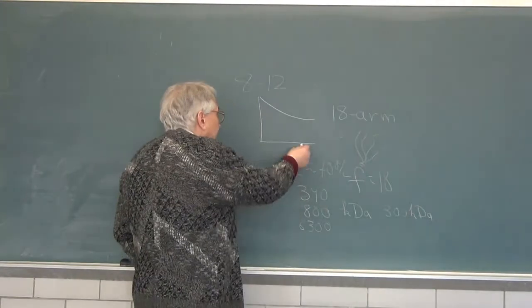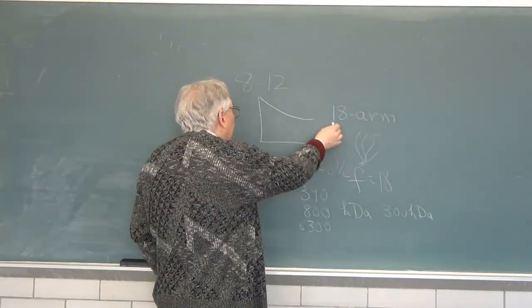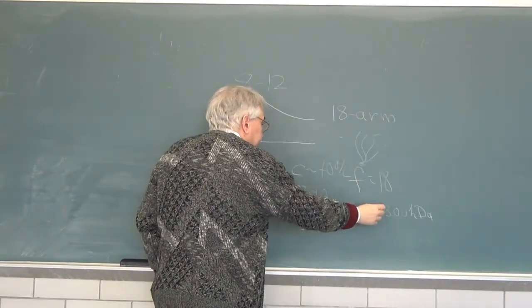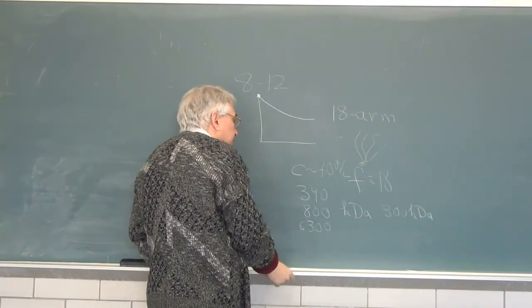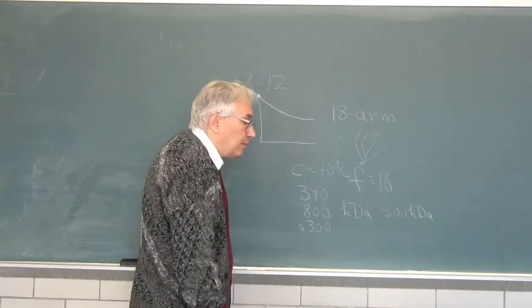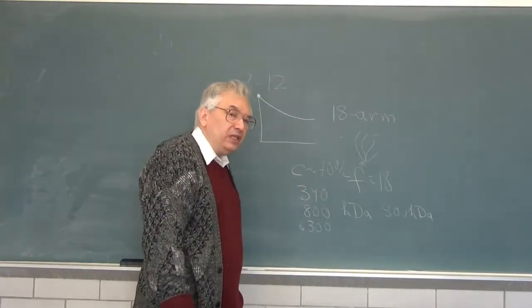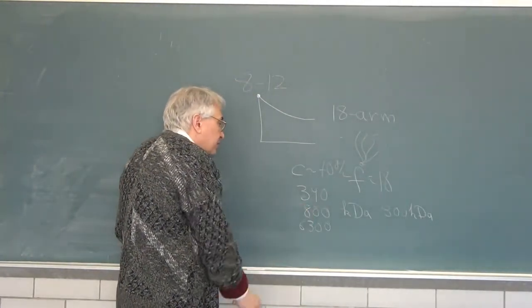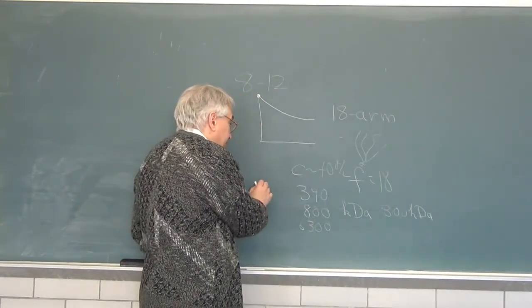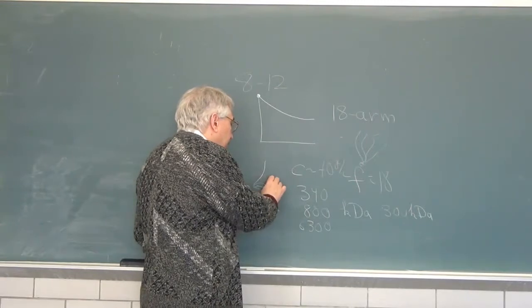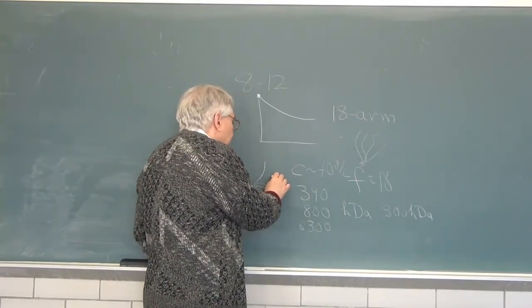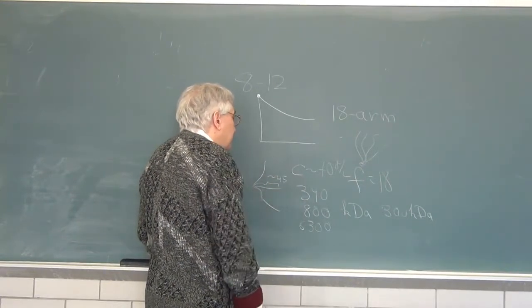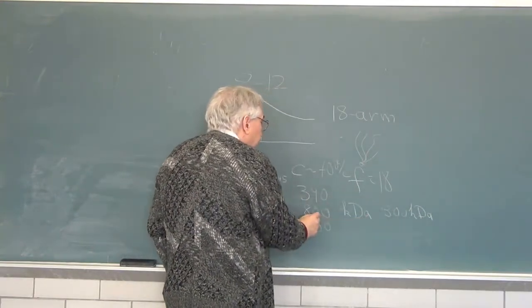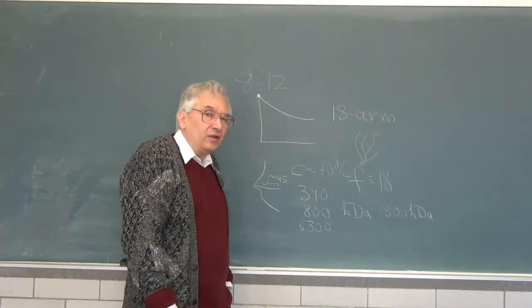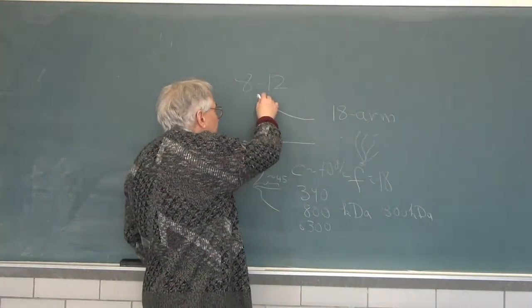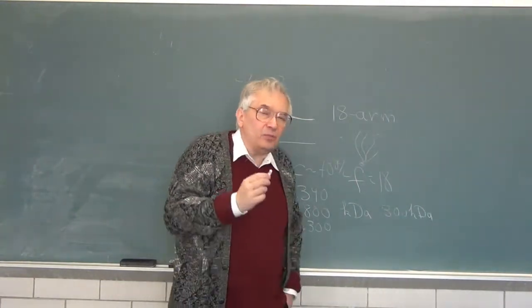They also, however, manage to find, it's the center of the three lines in the graph, a linear chain whose diffusion coefficient at low concentration is the same as that of the 800 kilodalton star. Now you should realize these are the molecular weights of the complete stars. If you have an 800 kilodalton material and it has 18 arms coming out, the molecular weight of one of those arms is not 800 kilodaltons, it's more like, round number 45 or a bit less kilodaltons. However, they find a linear chain, they find a star, the diffusion coefficients at low concentration are about the same, and as they take up the concentration, the two curves track each other with a reasonable accuracy.